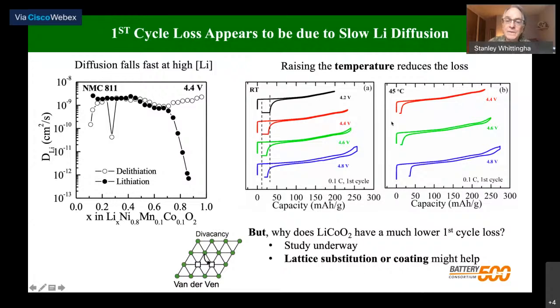If we now do this at 45 degrees instead of at room temperature, you can now see we've eliminated well over 50% of this first cycle loss. And this is at 4.2, at 4.4, at 4.6, it's not quite as good, and you see this separation. So now we're getting more and more reaction of the solid with the electrolyte, and it's much worse at 4.6 volts. So we can't go to these higher voltages at these higher temperatures. But clearly this is again an indication of diffusion limited.